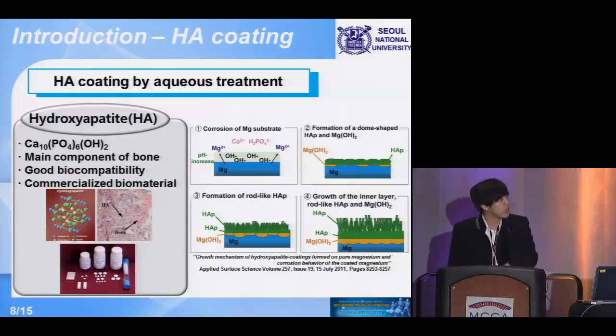And this is the simple principle of our HA coating. If we immerse the magnesium inside a solution which has a calcium source and a potassium phosphate source, the magnesium corrosion occurs, and on the surface, pH increases. Because of that, the hydroxyapatite forms on the surface, and it grows in a needle shape.